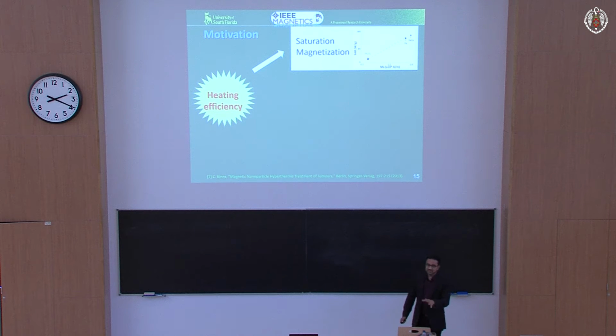Here there is a serious limitation, and this is again those three letters that I mentioned, FDA. The only FDA approved magnetic material for this is iron oxide, magnetite, maghemite. We don't have too much of a choice. We can't use Heusler alloys or any other type of exotic magnetic materials and show that we can make hyperthermia out of these. I've seen some papers in the literature reporting SAR on some exotic material, but it's DOA, dead on arrival. It's not going to go anywhere.